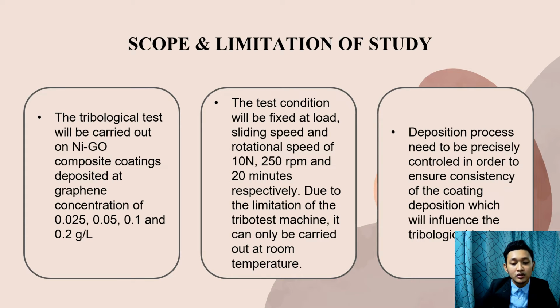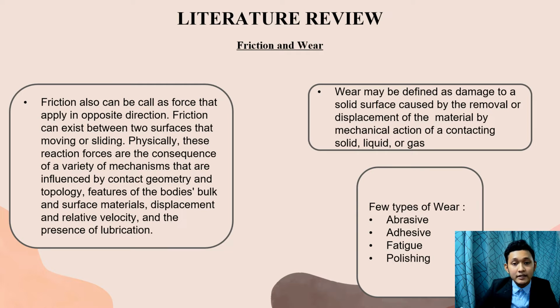Due to the limitation of the tribo test machine, it can only be carried out at room temperature. The deposition process needs to be precisely controlled in order to ensure consistency of the coating deposition, which will influence the tribological test.